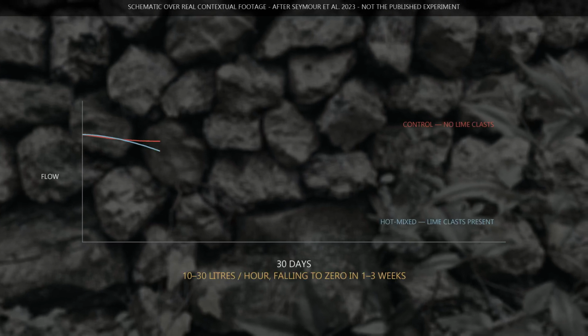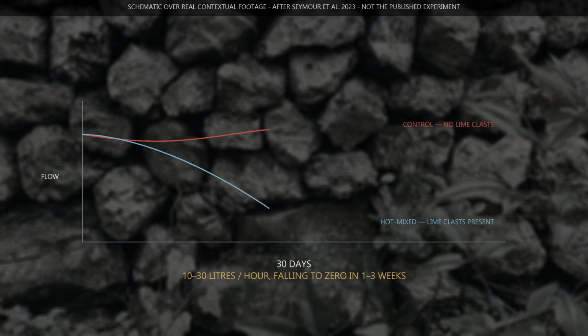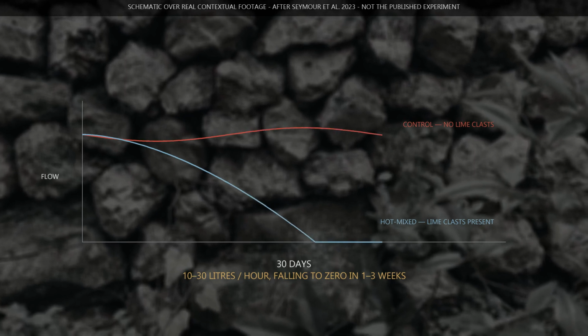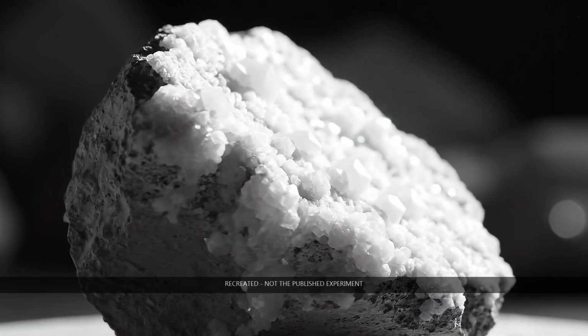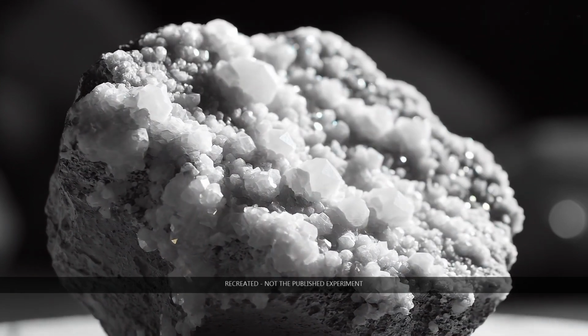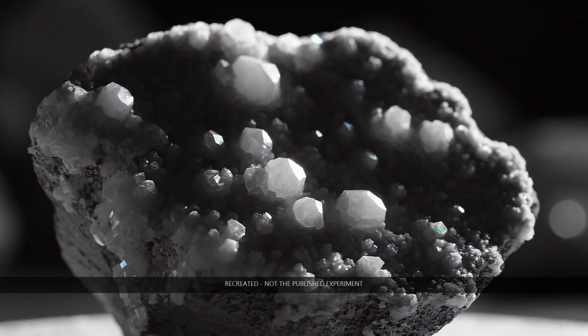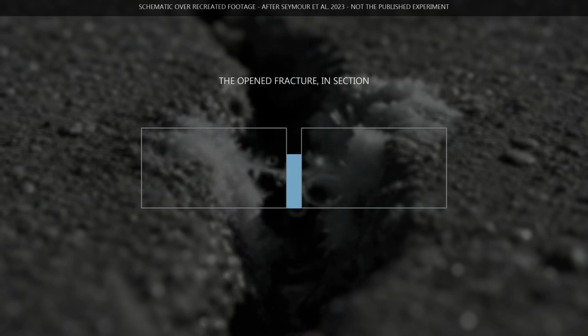On one sample, the flow fell away over 1 to 3 weeks, depending on the crack, until there was nothing. They opened it up. The crack had filled itself. A new mineral had grown inside it, calcite.